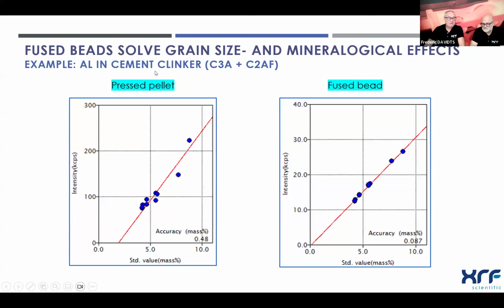A cement clinker, in this case, we're just analyzing aluminium. And we can see here on the left-hand side a calibration curve for aluminium based on the pressed pellet method, which, by the way, we will discuss in the month of November also. And on the right-hand side, we can see exactly the same calibration standards, but now prepared as fused beads. And you can see that the linearity and the accuracy of our fused bead method is much better than for the pressed pellet method.